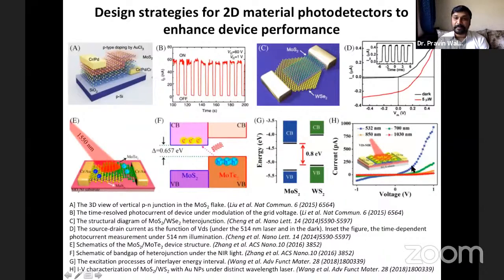And you can see here the IV measurements at various wavelengths. From 532 nanometers it shows very good current-voltage characteristics, but it is still sustained up to 1030 nanometers, right? So there is still photocurrent generation, though not very high responsivity, but it is there. Therefore, this strategy has helped you to widen the range of your wavelength, right? So these are the four important strategies people have used.